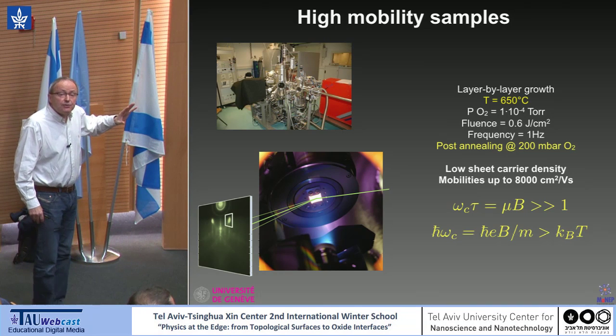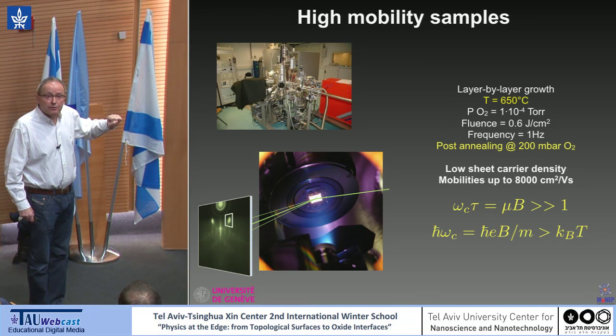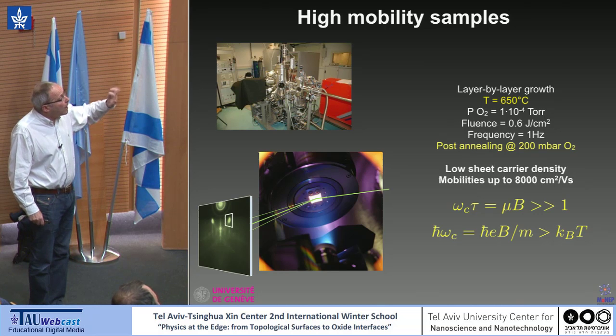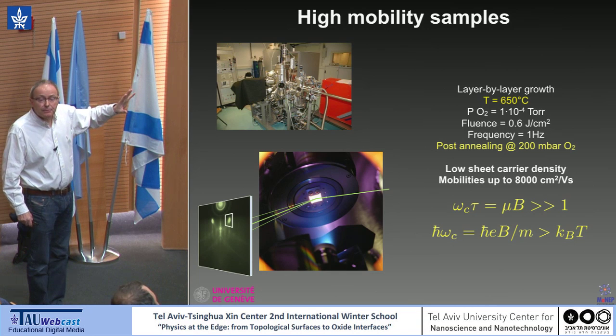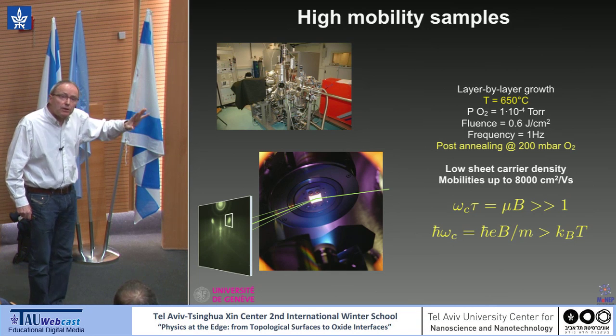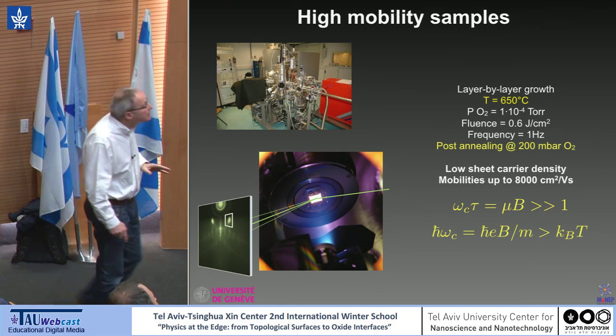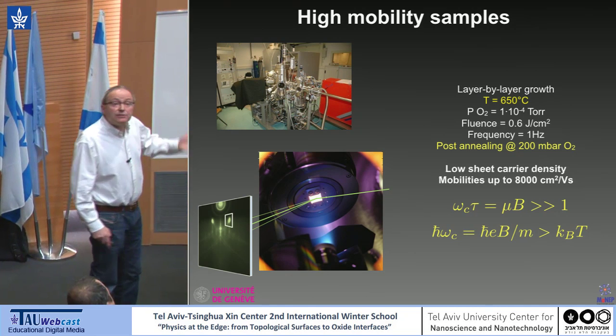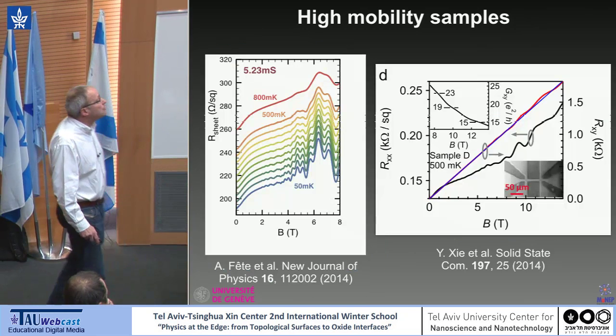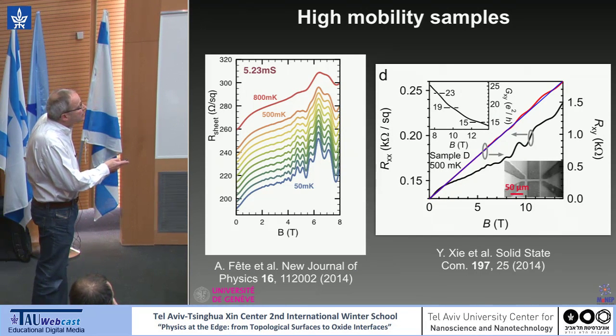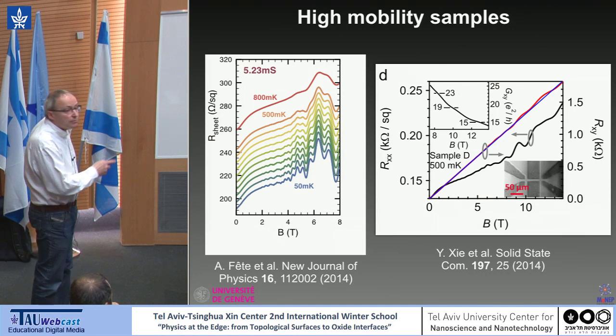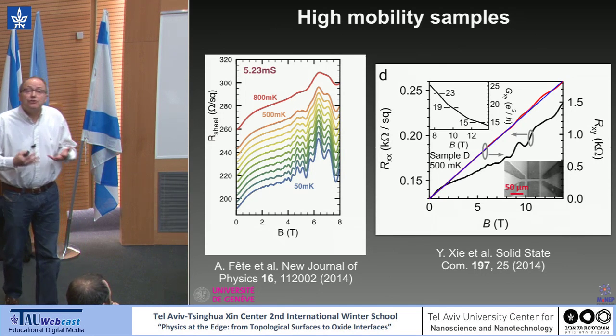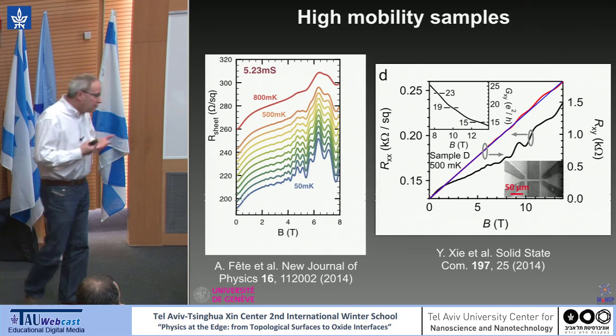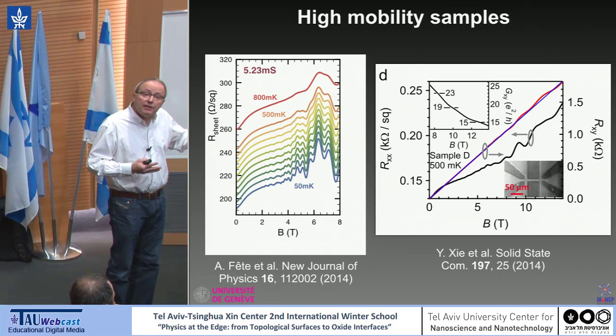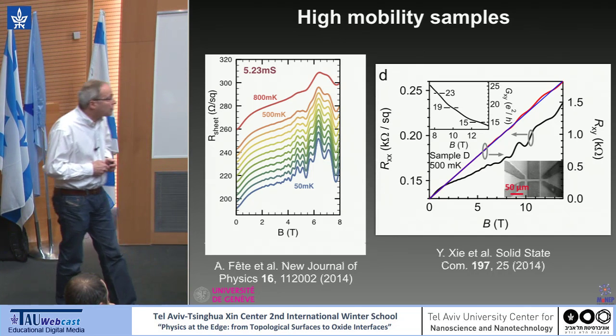We're able these days to get high mobility samples using different techniques. One way to do it is just to lower the growth temperatures. If you do this, you get lower carrier density and a high mobility. And we enter the quantum regime, and we can see Shubnikov-de Haas oscillations. You see here results from Harold's group in Stanford. You see here results from Geneva. And obviously, it's interesting to study these Shubnikov-de Haas oscillations, which will give us some information on the electronic structure.